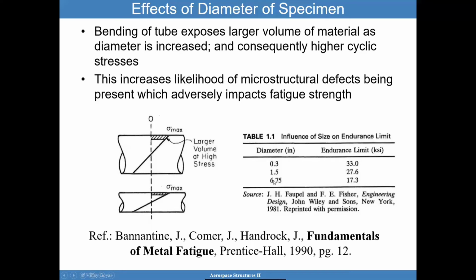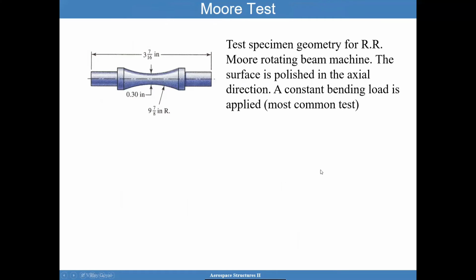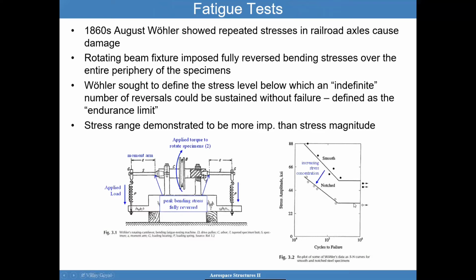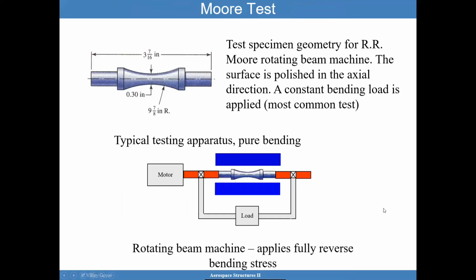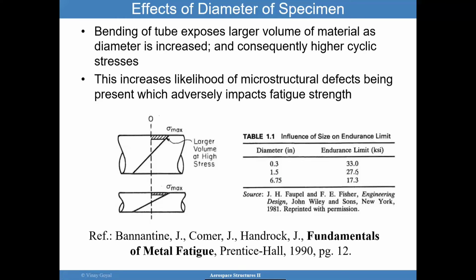When I went to a larger diameter, the endurance limit dropped. And what I mean by endurance limit, again, is when I got that infinite life situation. I'm trying to find this line here. So when the stress amplitude reaches a certain threshold, below that value, I don't seem to see fatigue. And so that is the point I want to make, that it was found that smaller diameter samples were impacted less than larger samples, particularly because the stress was acting over larger areas. So you have a larger possibility of microstructural defects in the sample.